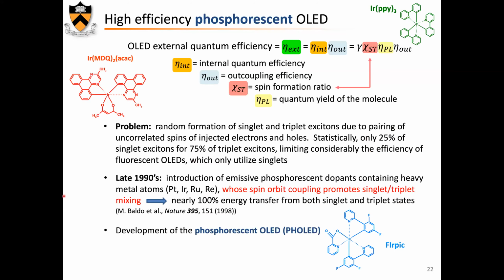So in the late 1990s, the group of Steve Forrest here at Princeton University came up with the idea of introducing in the material phosphorescent dopants. These phosphorescent dopants each have a heavy metal atom. Here it's iridium, here also iridium, but also platinum, ruthenium, rhenium, and so on. And the spin orbit coupling induced by these heavy atoms then promotes a singlet triplet mixing, which allows you to essentially use these 75% of triplet excitons. And then you get essentially 100% energy transfer in the system. So this paper was extremely important for the future development of efficient OLEDs.